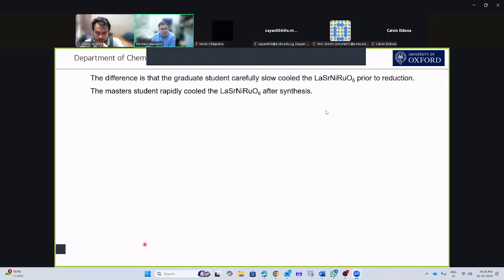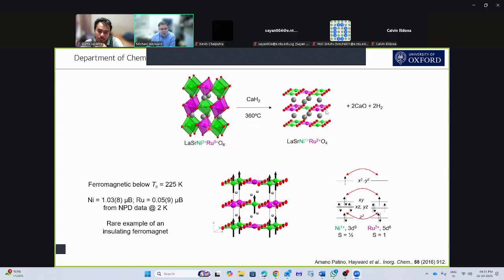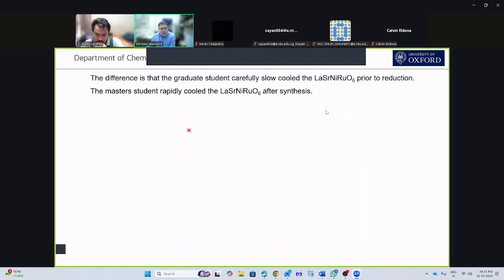Well, the difference comes from how you make the starting material. And it turns out that the master's student was in a rush. He just took the sample, this material, LaSr-NiRuO6, that you heat at 1100 degrees C, he just took it out of the furnace. Whereas the graduate student cooled it down slowly because she was worried about the disordering of the nickel and the ruthenium in this case. So she slow cooled the sample. And this is what changes the reactivity. And so if we do this carefully, we can see how it works.